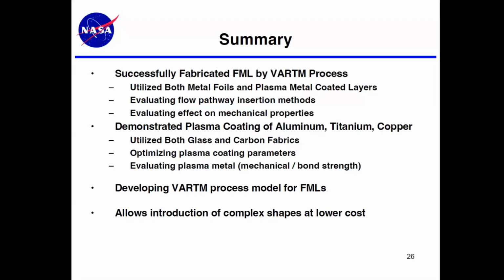Some of the applications, this is the last chart I have, I believe. Some of the applications, again, I mentioned are probably designed for non-fatigue driven properties. So that would be blast containment, say permeable or reduced permeability for gaseous containers. Lightning strike protection was one property that we were looking for, and we did test for copper on glass and building composites from that and the ability to protect for lightning strike. Current aircraft use an astrostrike material that's expanded copper that's placed on the outer layer of a composite after it's built. This would provide a method to put lightning strike protection within the composite itself and kind of build it into the structure instead of having to put it on later.